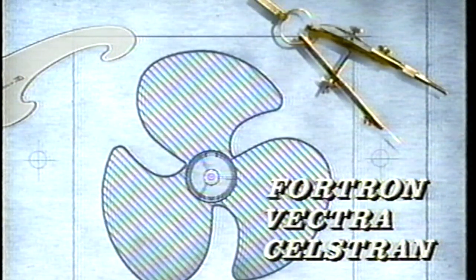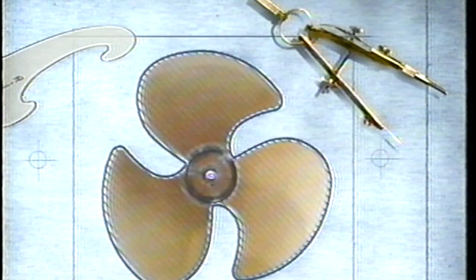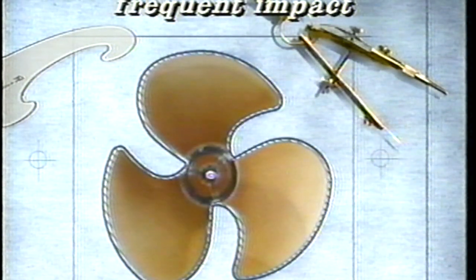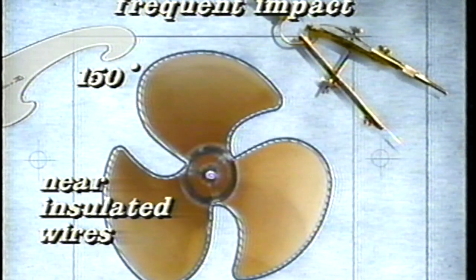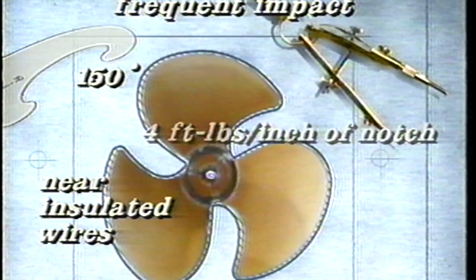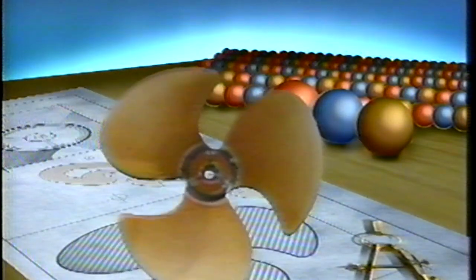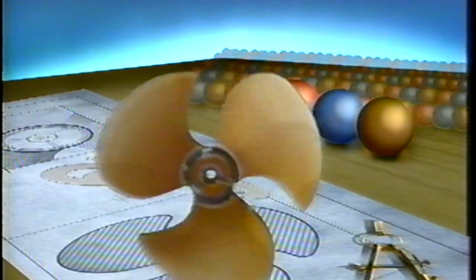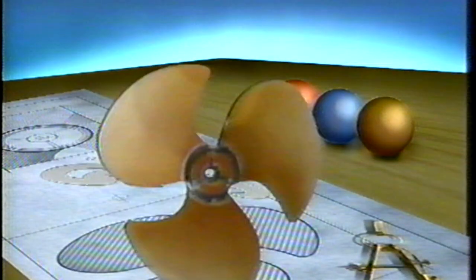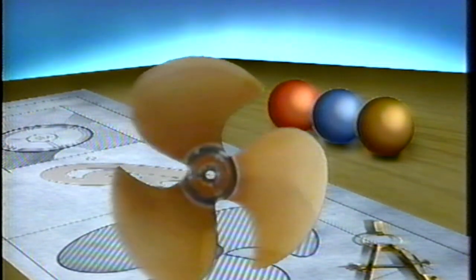An example, say we've designed this impeller. In end use, it will be subject to frequent impacts. It will also be subject to some slow loads and some heat, about 150 degrees Fahrenheit. And there are insulated wires nearby. But if the part cannot stand the impact of about 4 foot-pounds per inch of notch, those other conditions are really academic. Clearly, the limiting or primary characteristic is the impact resistance. If it's not sufficiently tough, it's totally useless.